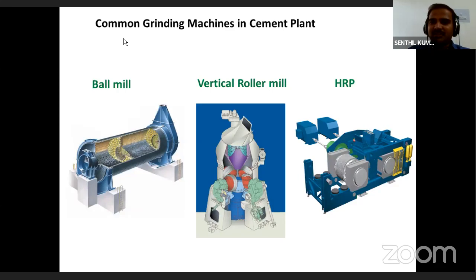We measure the moisture content of the input as well as the product in every shift. A shift is 8 hours, and in a shift we measure 2 times. So we check the moisture level and the mill outlet temperature, whether it be a ball mill, a vertical roller mill or a HRP. The product temperatures and the moisture levels, we collect the samples, of course. We collect representative composite samples and check the fineness levels. Along with the fineness level, we check the moisture content as well as the temperature.